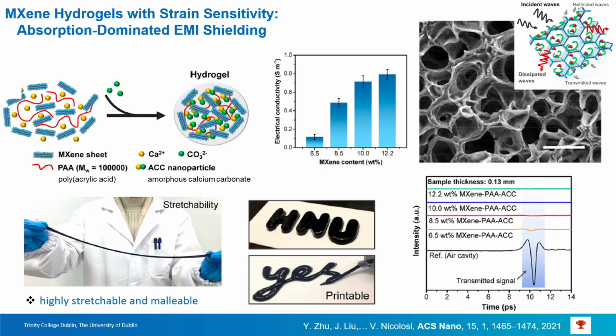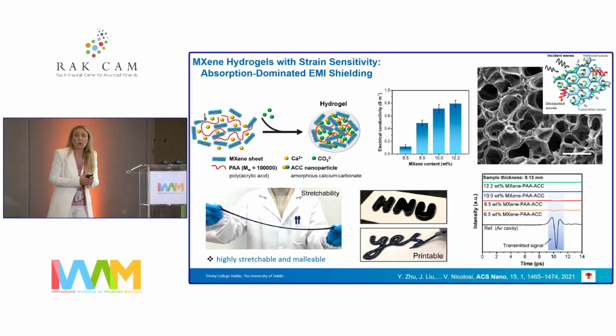It's a very, very hot topic, of course, and what we can do, using the properties that MXenes have with suitable polymers like polyacrylic acid in particular, is couple them with amorphous calcium carbonate to stabilize the system towards oxidation. And the nice thing that we achieve is that these hydrogels have this very nice hollow structure, which is the reason why they're very successful at electromagnetic interference shielding.